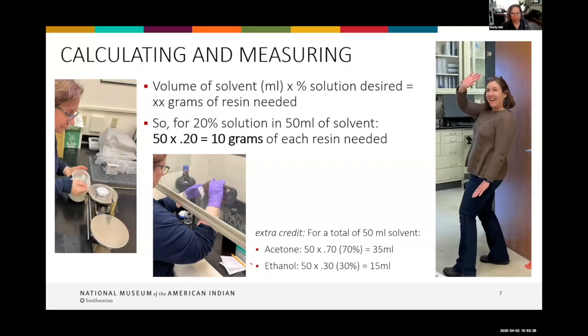But in this brass coating application, a slightly thicker coating can be useful, so we aimed for a 20% solution. To determine the amount of resin pellets to create the solution, you multiply volume, which is in this case milliliters of solvent, by the solution desired, which in our case was 20%, to get the weight of the resin pellets needed. So since our volume was 50 milliliters and we wanted 20% or 0.20, those multiplied by each other become 10 grams of resin pellets for each jar. And after Beth taught me how to do that, she happily walked away to let me fend for myself. So essentially she taught a mount maker to mix, which I am forever grateful for.